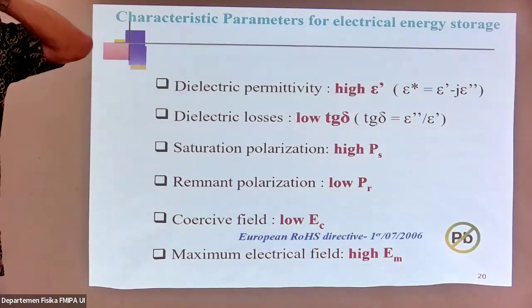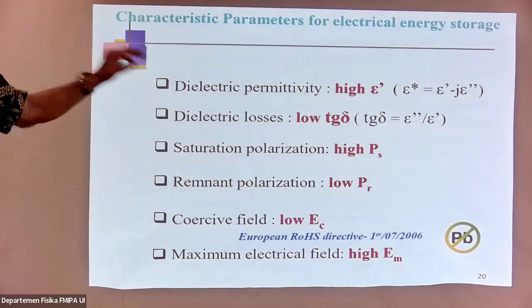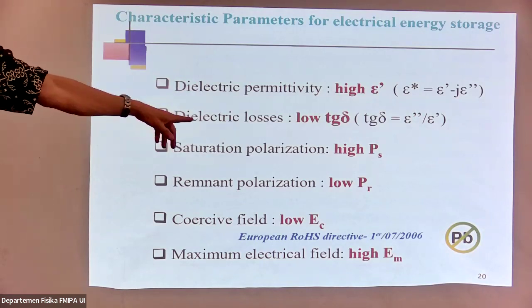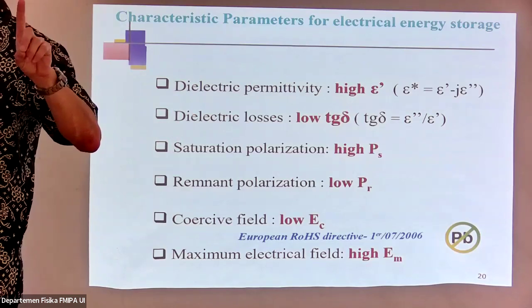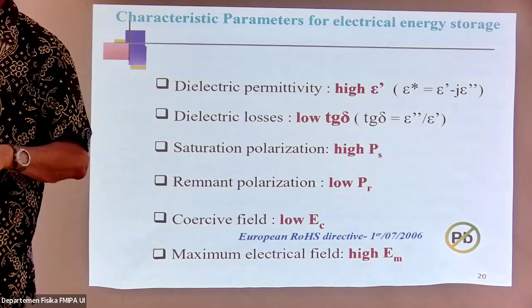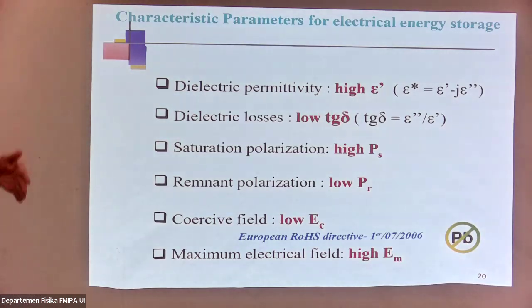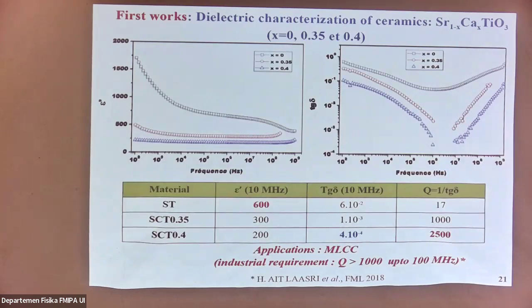But we have to keep in mind that it's only possible to increase this highest electric field if our material can resist breakdown. Because otherwise, when we study the limit of this kind of material in practice, we see the breakdown directly. We observe in the material, of course, a small thunder. You broke your material, electrically broke. So this is the first attempt we made with this material.